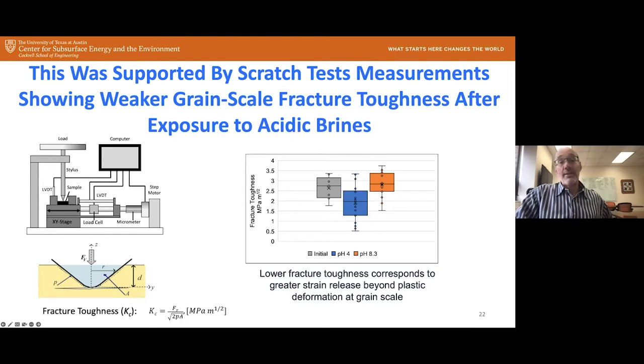The last thing we did, and this was over in Nicholas Espinosa's lab here in petroleum engineering at UT, was to perform scratch tests where we could measure the fracture toughness. So basically you have your sample, this yellow would be our sample of Bandera gray. And we did this on the original sample and then on that milled surface, both on the asperities and off the asperities after the experiments were performed. We take a stylus that's got a conical point down here at the end and it has a load on it. And so depending on our sample, that point depresses so far into the sample, just from the overlying force.